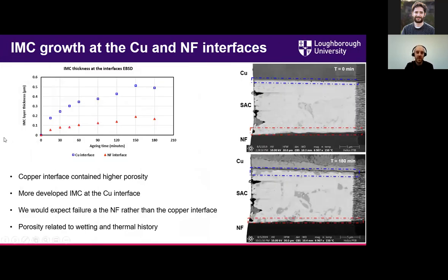So based on these results, we can track the intermetallic growth at each face, and we can start to comment on what mechanical properties we might expect from the joint. So from the copper face, both faces have a similar growth rate initially, and then the nanofoil face doesn't have as many IMCs grown, and it starts to slow down its growth rate, whereas the copper IMC layer seems to increase and then steady out later on.